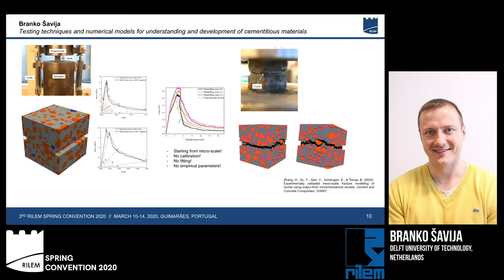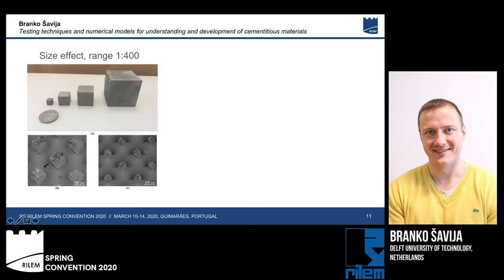We have also tried to use this experimental approach to study the size effect of hydrated cement paste. So concrete and other quasi-brittle materials are known to exhibit a strong size effect, meaning that the larger the volume that we test, the lower the strength that we measure will be. So we use these microcubes of 100 by 100 by 100 micrometers, and we created specimens with the same geometry of larger sizes all the way up to 40 millimeter size.